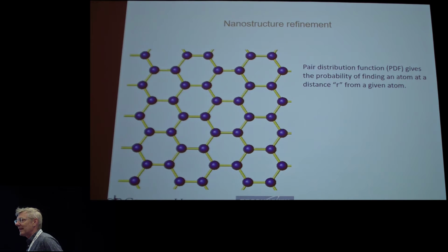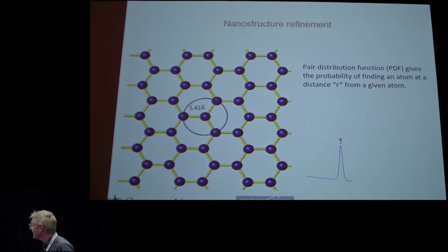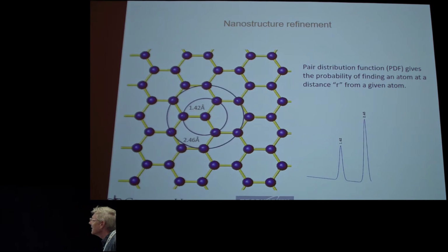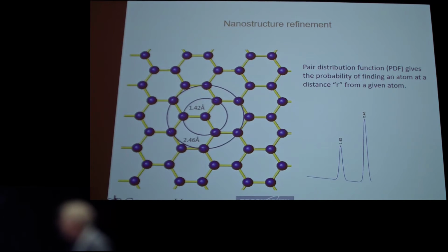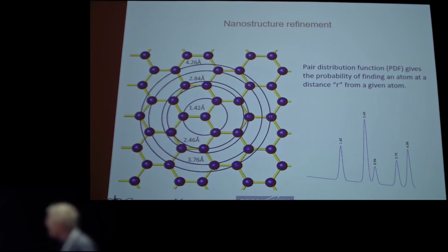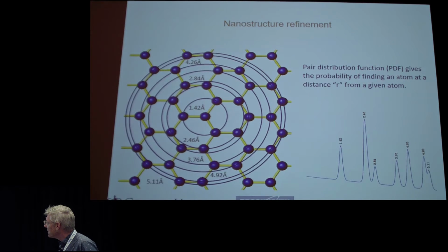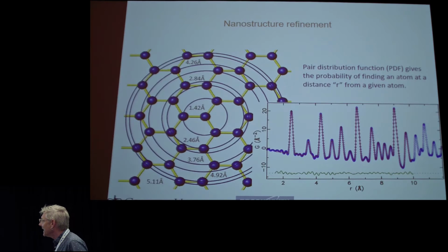So once we've collected a pattern, we can get these PDFs. We can also model them. It's fairly straightforward. You put an atom at the center, and then you go out some distance, and when you find another atom, you put a delta function, and you broaden the delta function to account for thermal motion, so it turns into a Gaussian. And we go out further until we find another one, another one, another one. And we can build up the whole PDF from the model. And we have now very powerful regression programs that can do refinements and fits. So we can actually extract quantitative structural information from the PDFs.